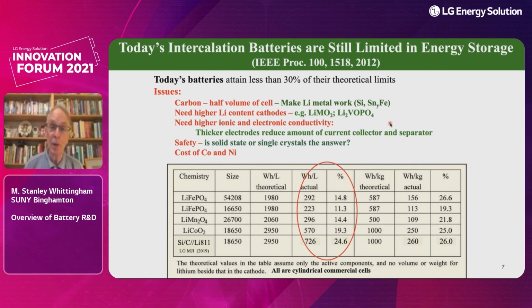Unlike TiS2, most of the present day materials, including the layered oxides, which are semiconductors, and the phosphates, are pretty good insulators. So if we can improve the conductivity, then we can make thicker electrodes, and reduce the amount of current collector and the amount of separator.